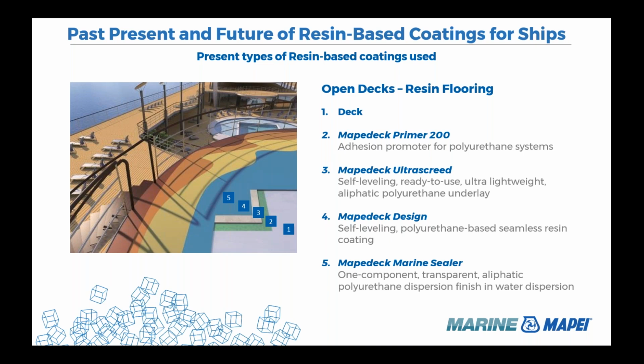In this case, you can see, first of all, one difference is that on item number 3, we are supposed to apply the Mapedeck Ultrascreed, which is ultra lightweight polyurethane aliphatic underlayment. The reason is, especially on higher decks, owners are requiring an even lighter system than usual. In this case, we made an example of the Mapedeck Ultrascreed to show and emphasize that with resin, which is already a lighter material compared to more traditional flooring, you can go even lighter in case of need, properly selecting the right underlayment for the scope.